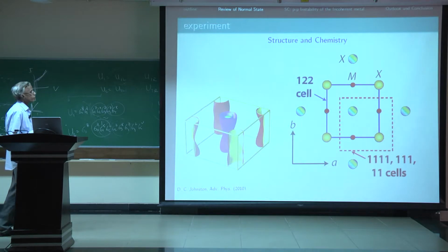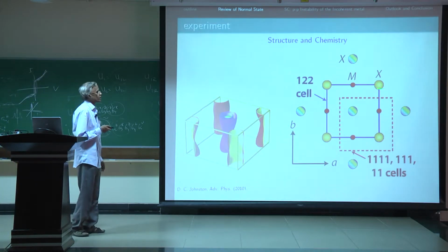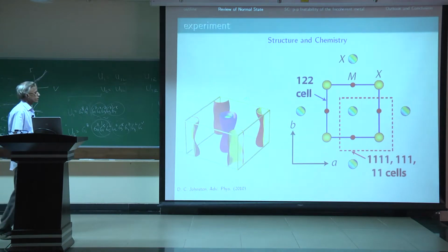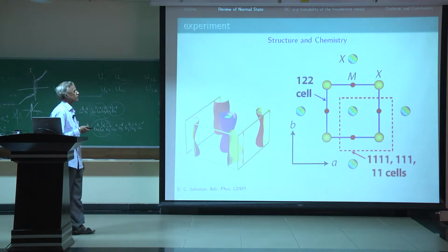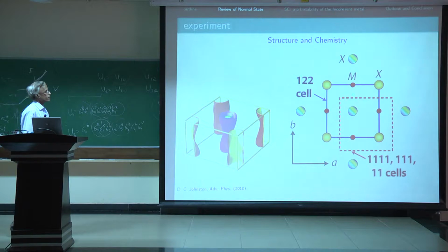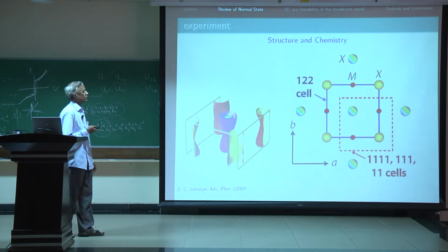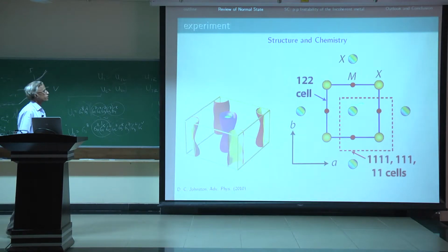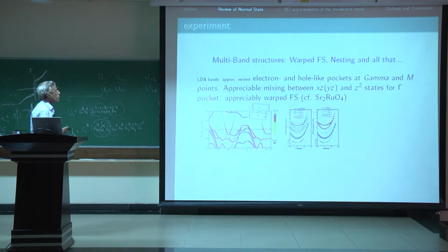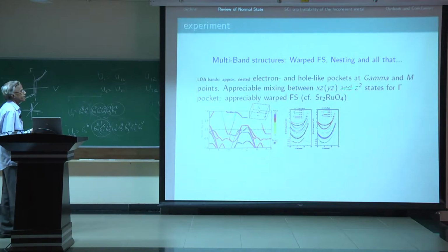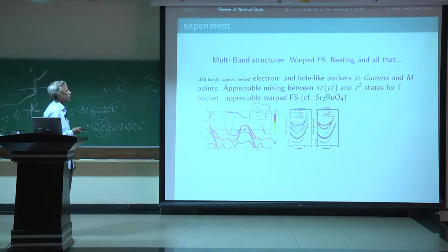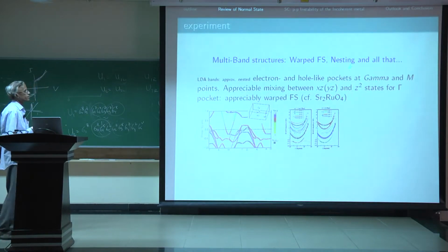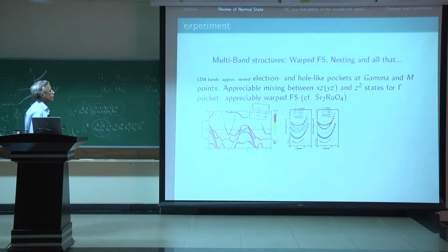Okay, so the first thing one worries about when one looks at a new material is the correlation between the structure and fermiology. In this case, there are 3d orbitals on iron which get split in a slightly different way compared to the perovskites by a crystal field splitting, which has S4 symmetry, but the 3d bands still cross the Fermi energy in band structure calculations, and the resulting Fermi surface for the 1-1-1-1 iron pnictides is sketched out here. You can get that kind of Fermi surface by doing a standard density functional calculation. In the tetragonal structure, the XZ, YZ orbitals are degenerate, but they are appreciably mixed with out-of-plane Z-square states for the gamma pocket, which is the central pocket.